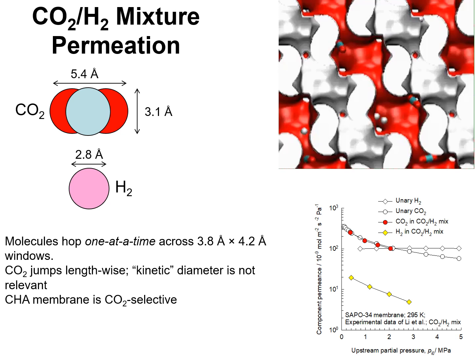On the other hand, CO2 is much more strongly adsorbed, and the permeance of CO2 in the mixture is practically the same as the permeance of CO2 on its own. The net result is that mixture permeation is strongly in favor of CO2.